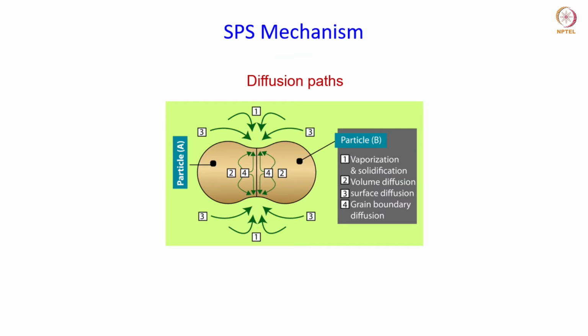And this is again a two-particle model showing the different diffusion paths which exist during the SPS process. These mechanisms of diffusion are not very different from what we have in case of solid-state sintering, except probably this vaporization and solidification which occur due to the intense localized heating as a result of the spark.